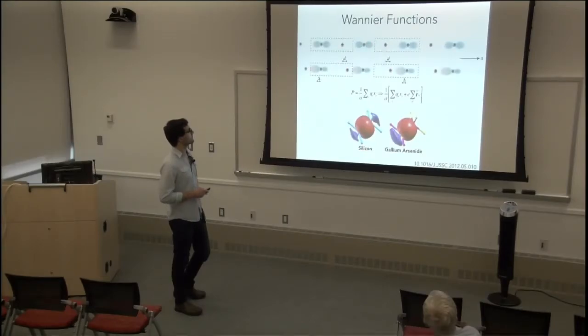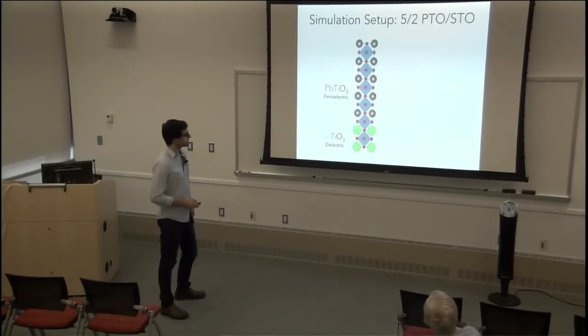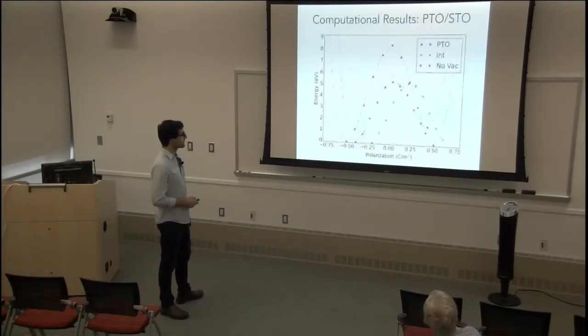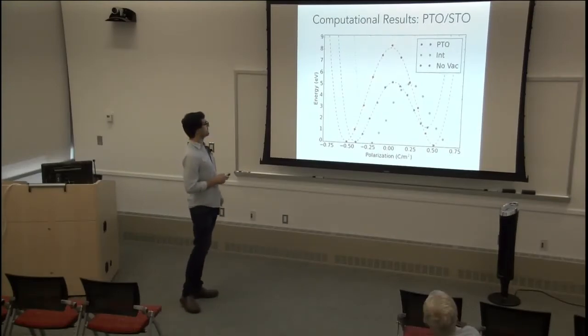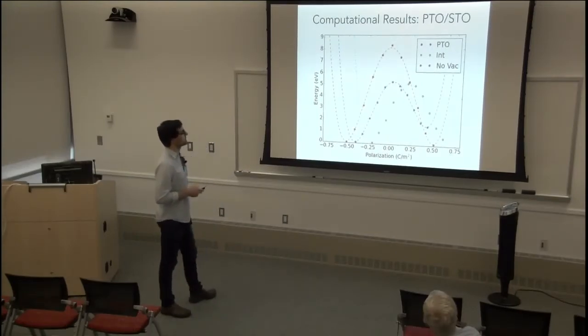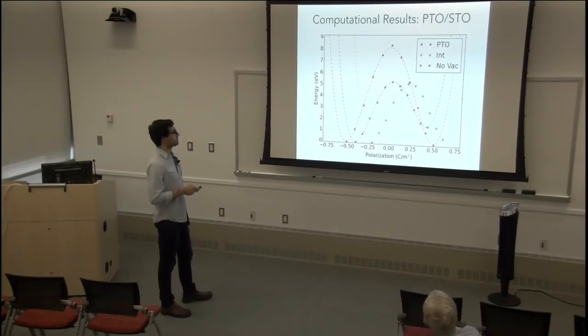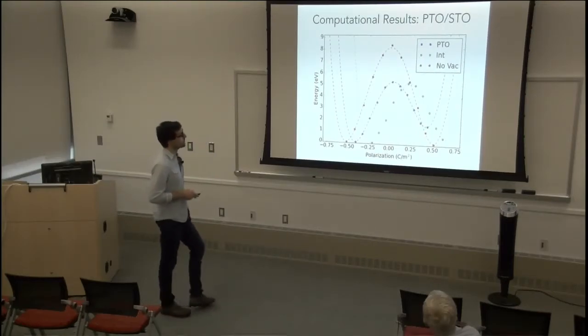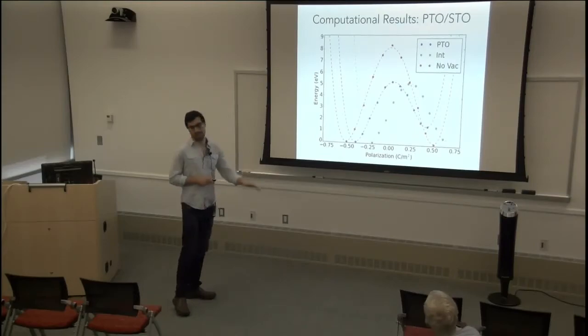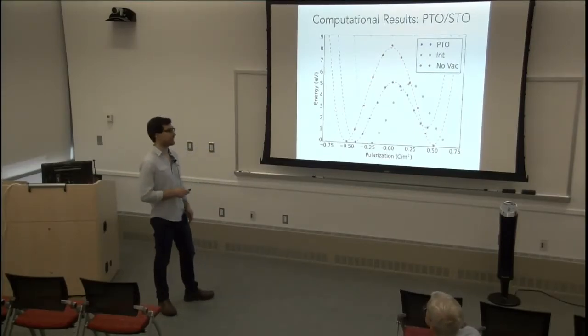So we're using Wannier functions. And what you notice is two things. The first thing is that the wall is not symmetric anymore. And if you remember what I told you, as you make the wall asymmetric, you create a bias in the hysteresis, which is what was seen experimentally.